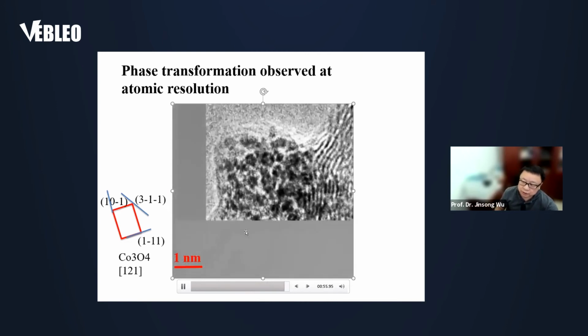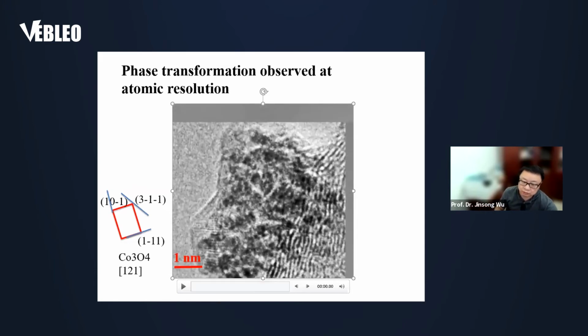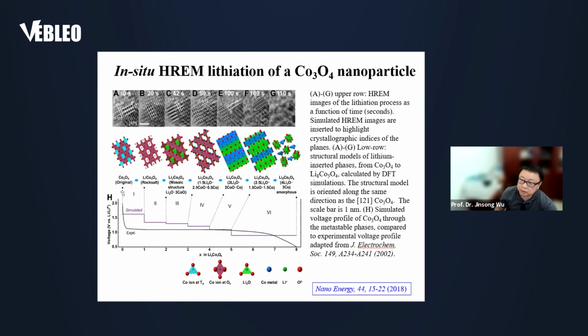So if we can observe the lithiation reactions at very high resolution, we can get more information out of it. And these are the snapshots taken from the video. By using DFT calculation, we can gradually calculate the structures by minimizing the energy. Based on the structure model, we can do image simulation and compare the simulated images to the experimental ones. Then we have very detailed information about the lithiation, especially about the intermediate structures, or what we call the metastable intermediate structures before the conversion reaction. So here's the first story.